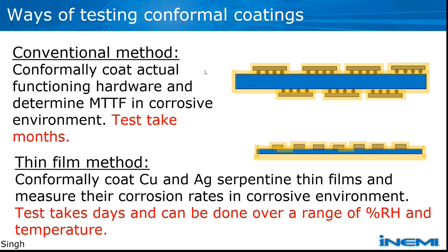Before the method we will discuss here, the conventional method consists of conformally coating actual hardware with the conformal coating under test and then determining the mean time to failure of that coated hardware when exposed to corrosive environments. The conventional test takes a long time - it can take many months up to a year - and often requires very high temperatures.